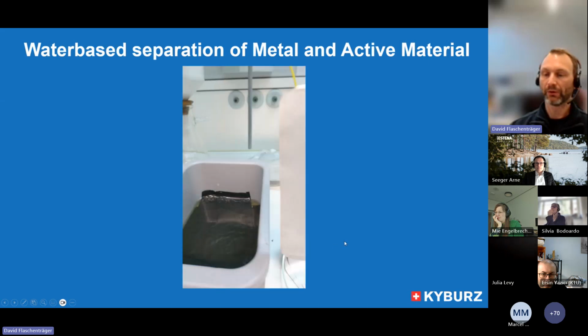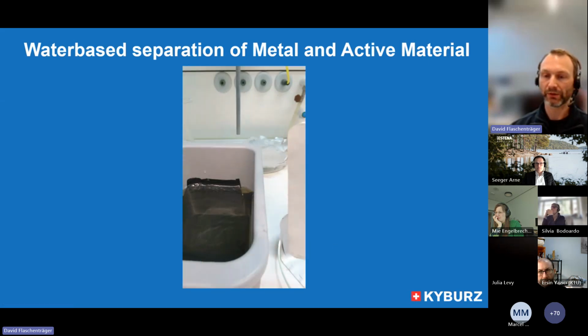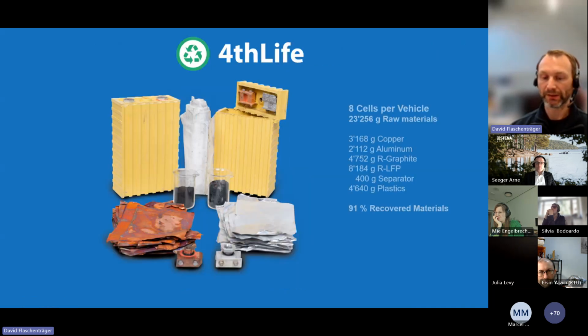And the really cool thing about this is that you need little to no chemistry, little to no energy, and you end up with a very high quality product. So in our case, with an example from our vehicles, where per vehicle we mount 8 cells, which are in total around 23 kilograms, we can recover more than 90% of the materials without the use of any chemicals and without the use of any large machinery. Of course, mainly the recycled LFP, followed by graphite and copper, and smaller amounts of aluminum and plastics.